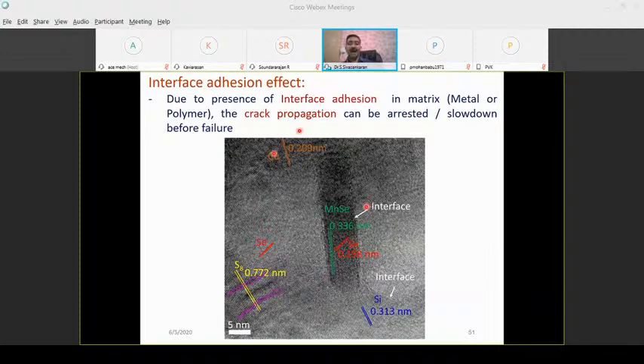You see, this is a highly magnified TEM image. You see one material, one phase: manganese, selenium, mixed with some other copper lattice, silicon lattice, selenium lattice. All are different materials, all at the atomic level. This is my research work, and this is the interface.